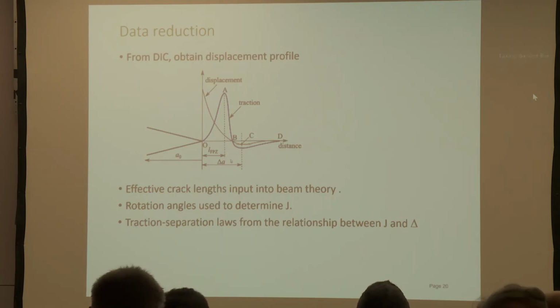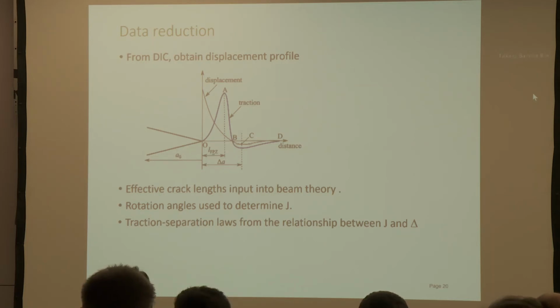So if we're looking at a diagram here, you can see that the region O to A is typically the region where we are representative of damage ahead of the crack tip. And the region A to B is the elastic tension region. And then for the sort of materials that we're looking at, bonded joints, we then have a compressive region. What we can then determine is, well, what is the correct crack length to be using in our analysis. So typically one would think that the effective crack length should be the value A0 plus the length of the fracture process zone, LFPZ, taking you to point A.